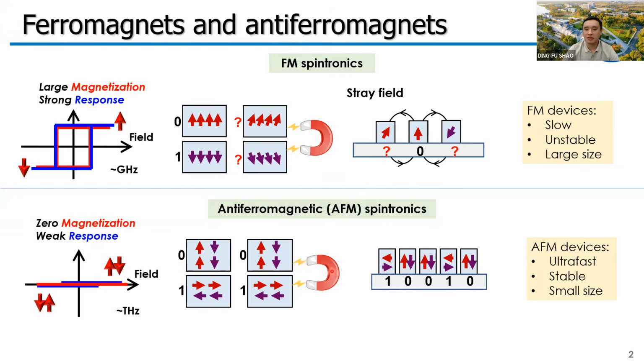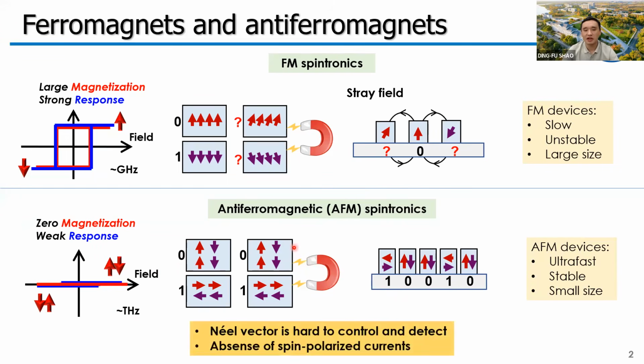All these are very promising. However, the antiferromagnetic order parameter, the so-called Néel vector, is very difficult to control and detect, which restricts the realistic application of antiferromagnetic spintronics. And this is largely due to the absence of spin polarized currents in the antiferromagnets we usually considered.